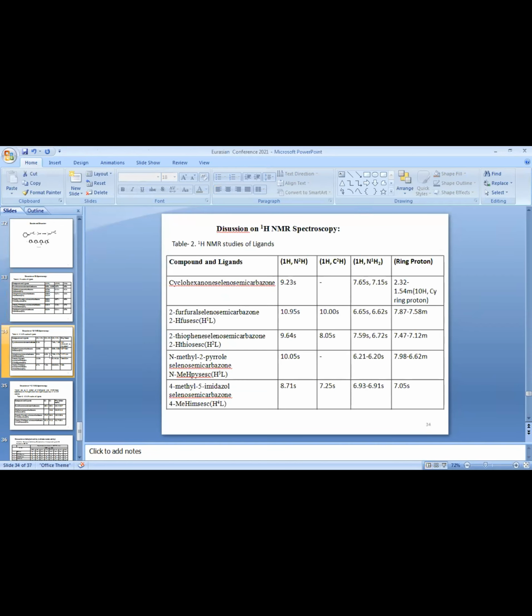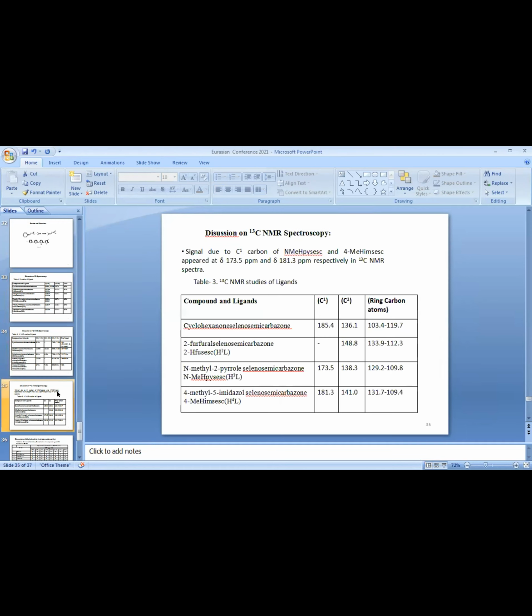Now, discussion from the proton NMR. If we explain the cyclohexanone selenosemicarbazone, the peak shows N2H at 9.23, and the NH2 proton signals appeared at 7.65 and 7.15, and the ring protons of cyclohexanone selenosemicarbazone are in the 2.32 to 1.54 range. And if we explain the synthesized ligands, they show the N2H signals at about these points. They indicate that the selenosemicarbazone ligands have been synthesized.